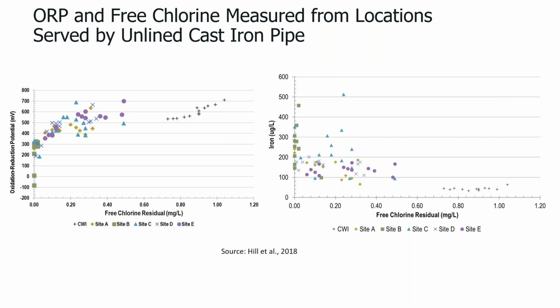In this work, this was a system that was evaluating the effectiveness of flushing of unlined cast iron pipe. And so these dots here, this is comparing free chlorine residual to oxidation reduction potential. In our distribution systems, the ORP is very much controlled by our disinfectant residual. And this is what we call the clean water interface.